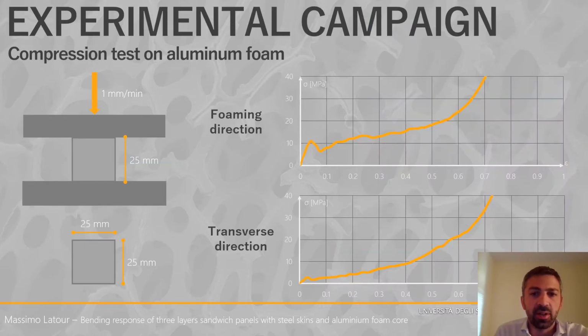The results of the compression tests are summarized in this slide, and characterize the behavior of the aluminum foam, which is different in the two main directions as said above. In particular, this material provides higher resistance in the foaming direction, so in the direction which is longitudinal to the direction of the panel, while in the transverse direction they provide lower compressive strength. In this case, it was about 1/3. In the foaming direction, the resistance was of about 10 megapascal. The main feature of this material in compression is that they have a very large strain hardening capacity without any loss of resistance, and in particular they arrive basically at a point where they reach a full densification of the material with very large strains.